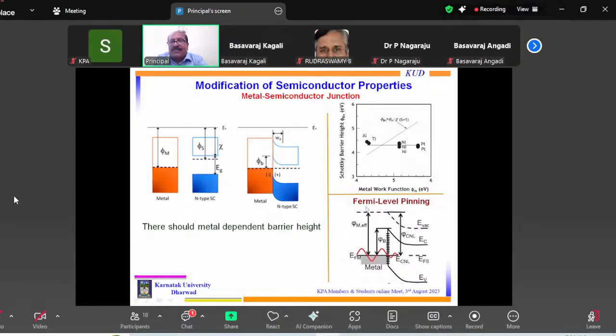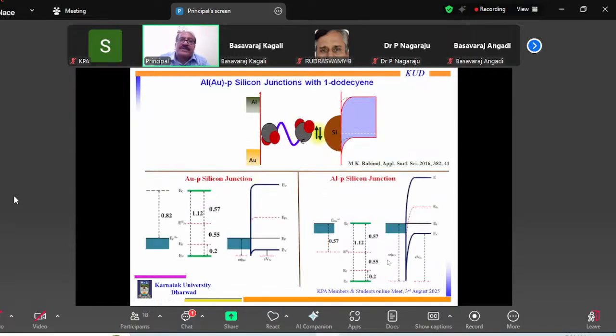Therefore, this is referred to as Fermi level pinning, and this is what we try to attempt by creating molecules at this interface. So this is the concept of our work. What we did is, there is a semiconductor, a silicon atom. You have a molecule. You can make the molecule bind covalently. Then I change the contacting metal. I can go from aluminum to gold. If I do so, I can change the work function by almost 1 electron volt. Aluminum has a low work function, whereas gold has a large work function, almost a difference of 1 electron volt.